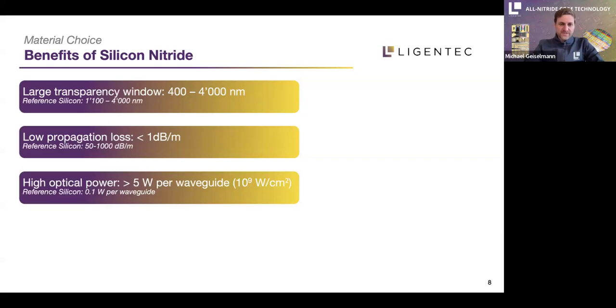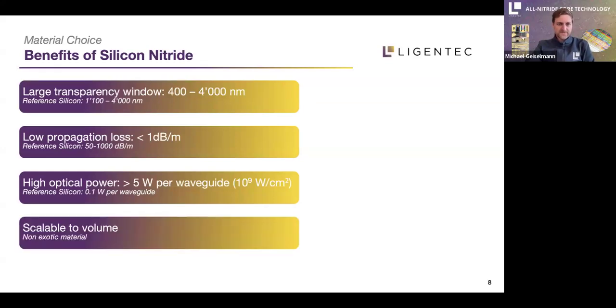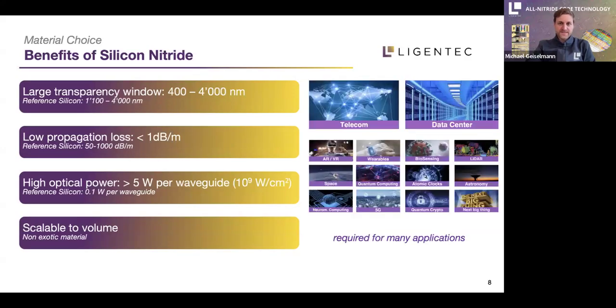And that is always in reference to silicon, and I don't want to do a direct comparison here. This is just orders of magnitude higher than in silicon, and orders of magnitude lower loss than in silicon. And the beauty of that material is that it's scalable to volume. It's a non-exotic material, so we have that installed in a high volume CMOS fab, and that is benefiting customers not only in the areas of telecom and datacom, as we have them as the markets as of today, but required for many other applications that I already mentioned.